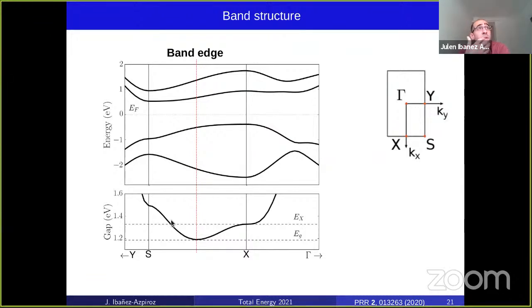Now, the most important physics happen close to the bandedge. Here in the upper panel, we show the band structure, and in the lower panel, the direct band gap. The bandedge lies somewhere between the S and X points, here pointed by the red dot, and the direct minimum band gap is 1.2 eV. Note also that there is a saddle point at the X point at approximately 1.3 eV. So we can say that the bandedge region lies between these two energies.